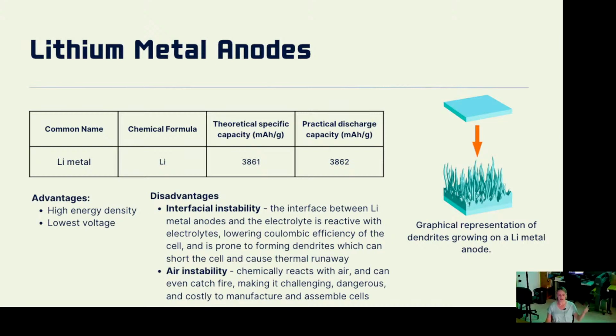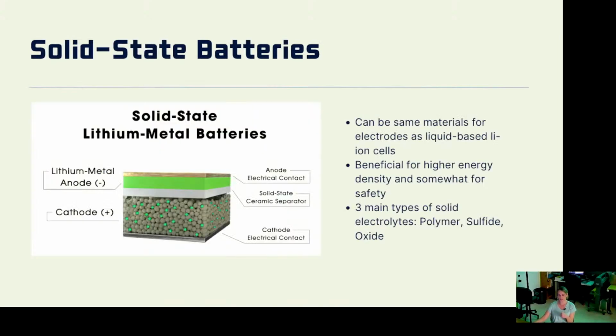And also a challenge is, this drawing here shows the formation of dendrites, which are like spikes. So as you cycle the battery and the lithium's going back and forth between the anode and cathode, picture it like a traffic jam. If the lithium can't react with the surface or form on that surface of the lithium metal, it can start building these spikes that can come out, puncture through the separator, which would then create a short circuit across the electrodes. That's when you get heat generation, thermal runaway, fires, and all of that. So a lot of research right now is going into different kinds of passivation materials on the surface of lithium metal anodes and other techniques to try to prevent dendrite formation, which leads me to solid state batteries.